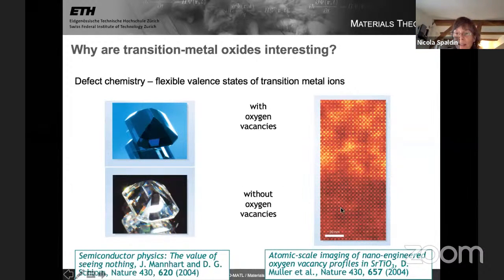And on the right-hand side is a high-resolution transmission electron micrograph of, this time, a thin film of strontium titanate, which has been treated to be oxygen rich, so almost stoichiometric. And in the upper part, it's been grown in an oxygen-poor environment, so it has many oxygen vacancies. And the upper part is conducting and the lower part is rather insulating in this case. So this again adds to the richness of transition metal oxide behavior.